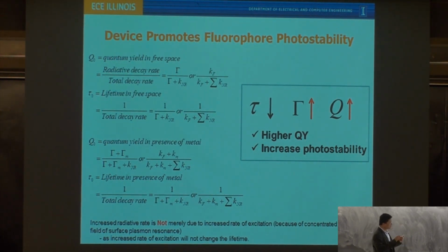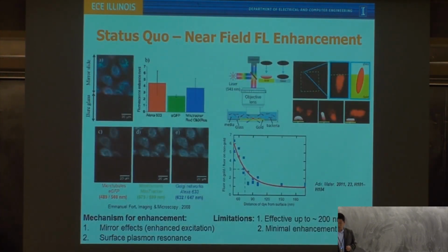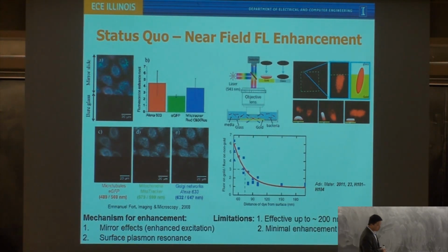I just want to show you this: so-called surface enhanced fluorescence has been demonstrated by many groups for many years. That's not a new thing. People do use that to do enhanced fluorescence imaging of cells. This example is not my work, it's from somebody else. They patterned the surface, one area with gold coating, the other area without. They see the fluorescent intensity from the cell on the gold-coated surface is much higher than on the non-coated surface. The enhancement is about a few times, from 4 to 6 fold, because of the simple mirror effect, you just reflect more light out. There's no nanostructure there, only a smooth film.